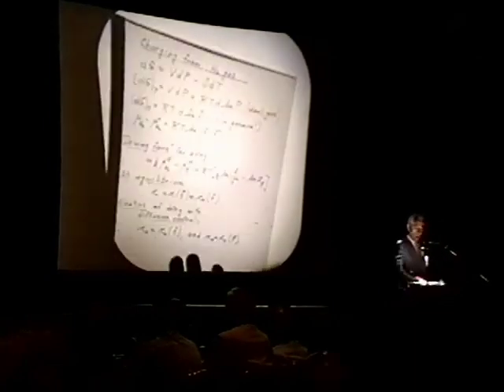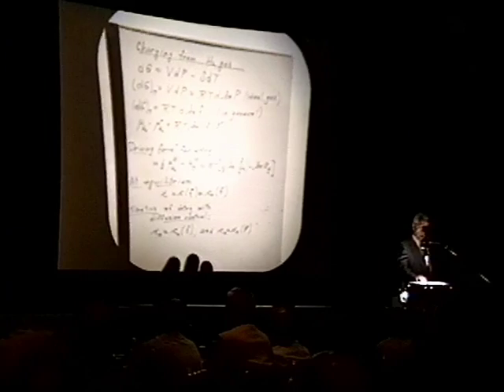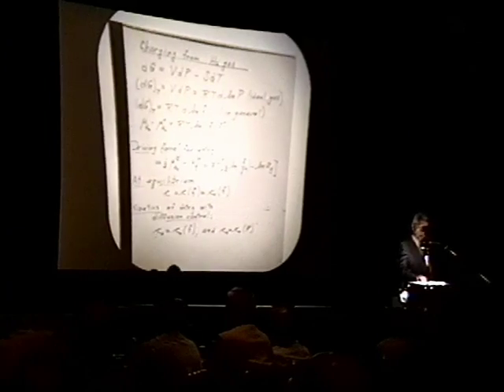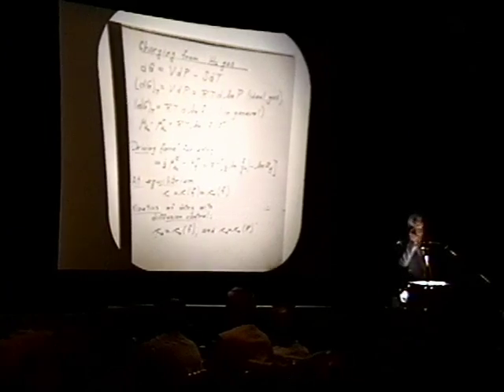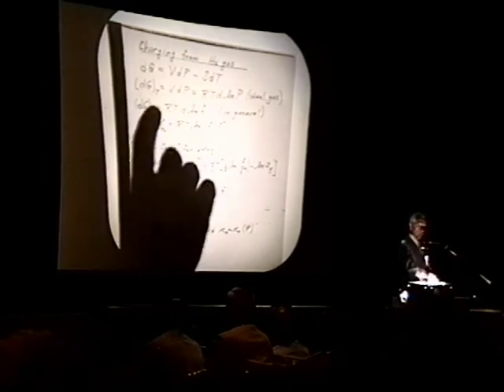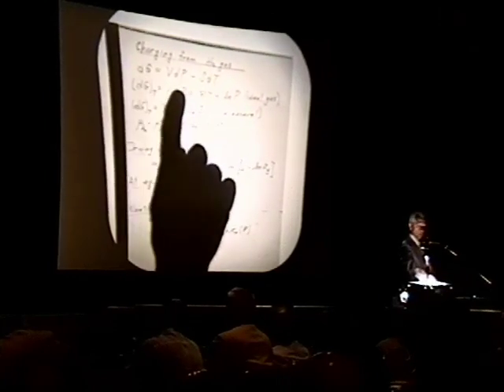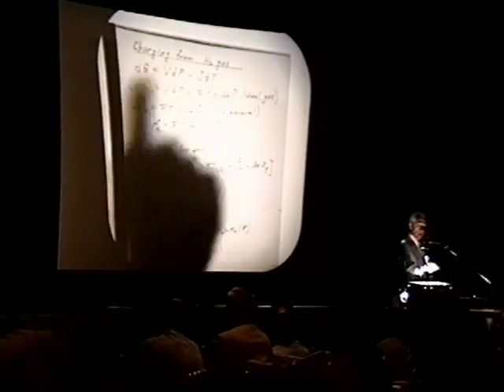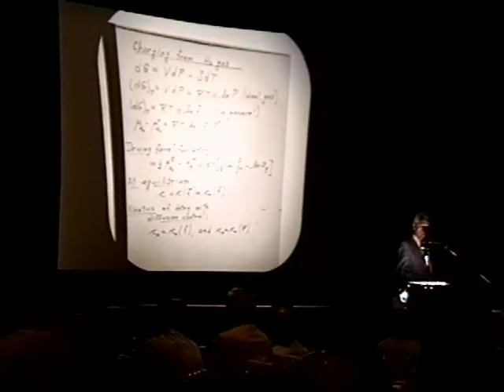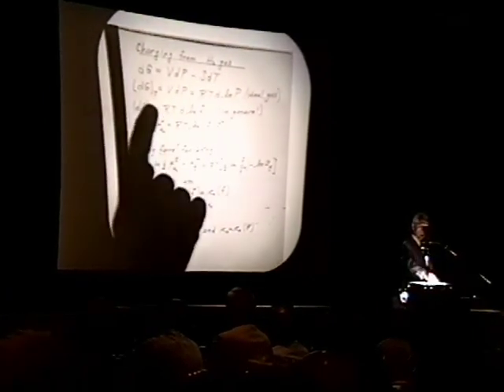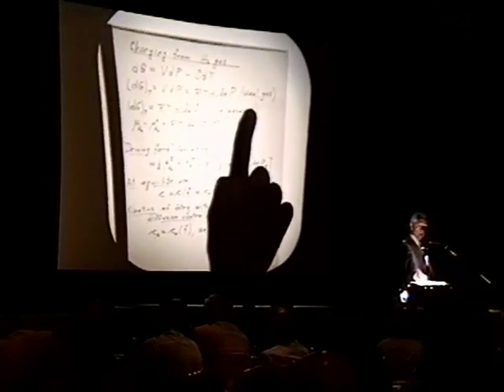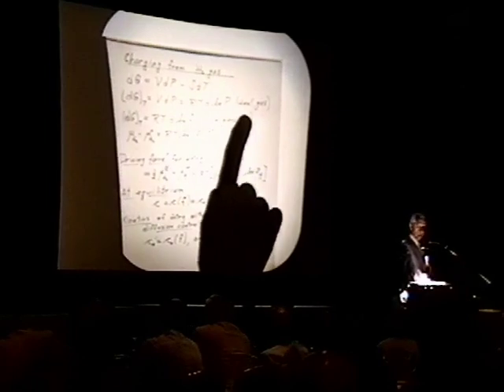Now I wish to discuss the problem of effective fugacity, which has made problems for some of us in the past. The fugacity is a thermodynamic property which comes about from one's desire to express the change of Gibbs free energy in terms of other parameters such as hydrostatic pressure and temperature, S being entropy over here. If we carry out a process at constant temperature, the change in Gibbs free energy is given by a simple expression, which for an ideal gas, using PV equal to RT, becomes this.